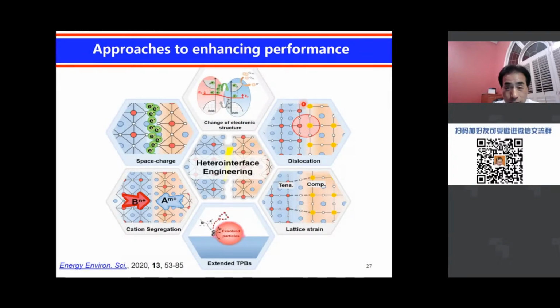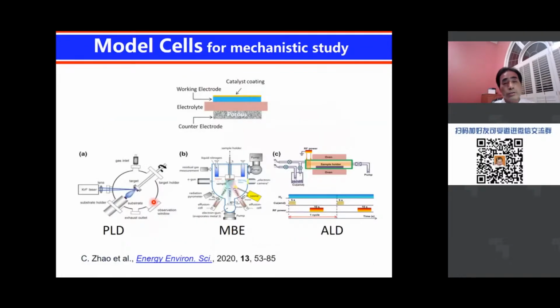You can also create different defects, for instance, dislocations. You can change the electronic structure near the junction area, or create a space charge region. This is accumulation of charge at the interfaces, or through cation segregation or enrichment that could create unique interfaces. All those are possibilities to enhance performance. So typically we use a model cell. By model cell, that means we have precise control of the geometry of the electrode. So often we're going to use PLD, even molecular beam epitaxy, or ALD, atomic layer deposition. Those give you very precise control of the electrode surface and the interface.